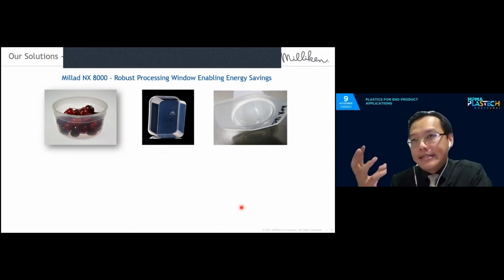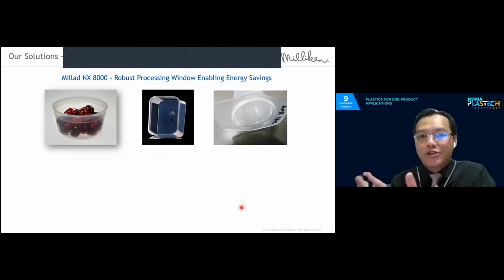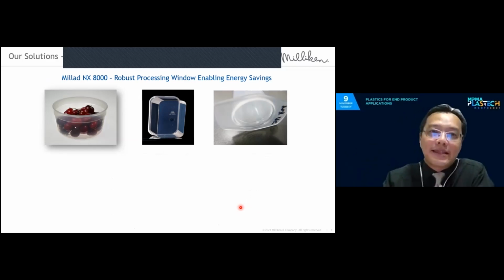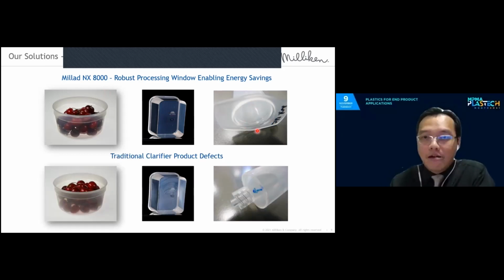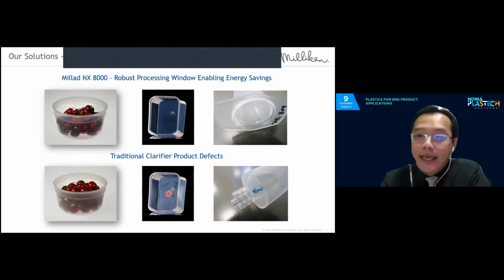Not just the overall haze or the overall transparency that you get the benefit from Millad NX8000, you also get less defect and no voids. Because if you try to use the traditional clarifier random copolymer PP, especially if you try to reduce the injection temperature, like we say, it gets hazier, less transparent, and there is usually higher risk and probability of defects, such as white streaks, white specks,